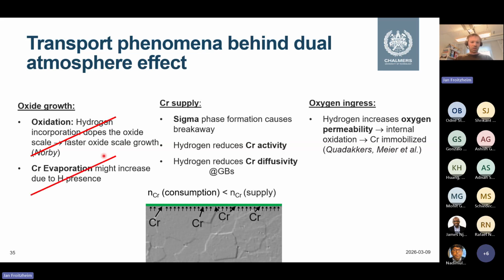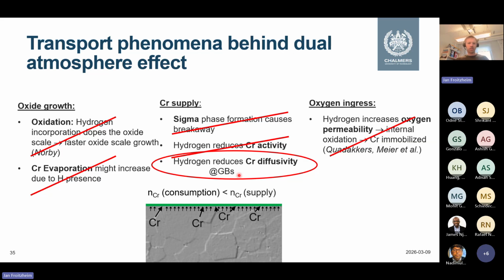Chrome evaporation, we looked into that. We love chrome evaporation, but it doesn't really explain this. We looked at other things like sigma phase formation, hydrogen reducing chrome activity - this was something we thought for a while might be the case, but we have also thoroughly disproven that. So in a way, maybe the most likely hypothesis right now is that hydrogen affects the chromium diffusivity, in particular at the grain boundaries. That's what we believe, but we don't really have full evidence right now.